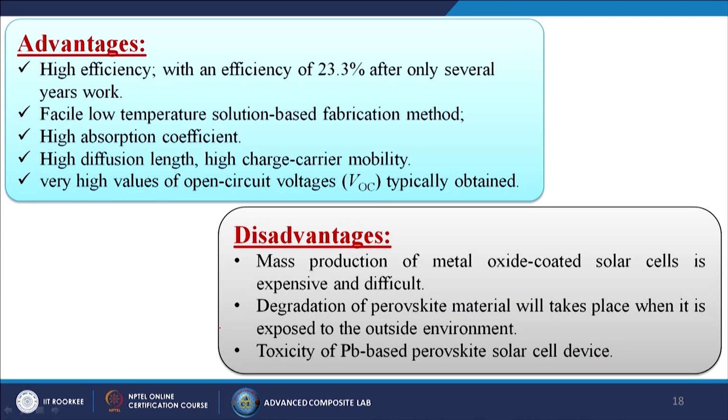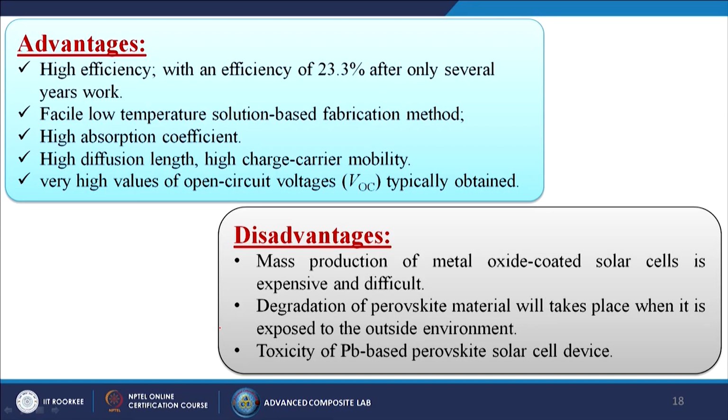First of all, it has a very high efficiency, 23.3% after only several years of work. It was achieved in the year 2018, but till today we have achieved up to 23.7% efficiency. Other advantages are facile low temperature solution based fabrication methods, high absorption coefficient, high diffusion length, high charge carrier mobility, and very high values of open circuit voltage typically obtained. So, these all are the advantages of these particular materials.